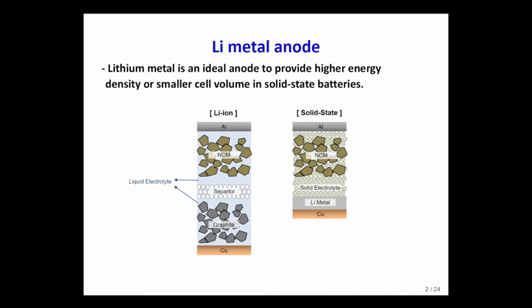Anyway, solid electrolyte is mechanically robust and is a kind of single ion conductor. So it is believed that it can handle the lithium metal anode very well. Lithium metal anode can offer much higher energy density than conventional graphite anode. You can see in this illustration that the volume of anode is substantially reduced when we use lithium metal anode.